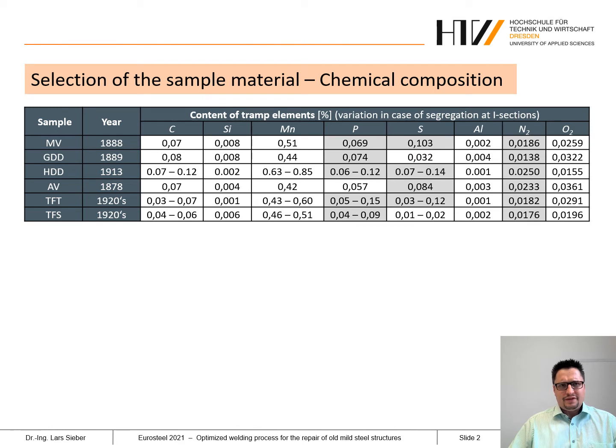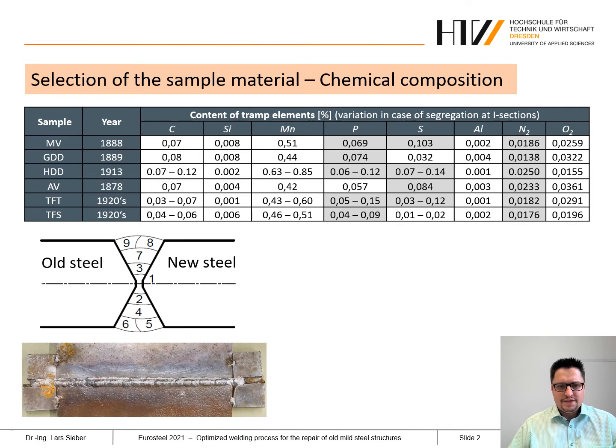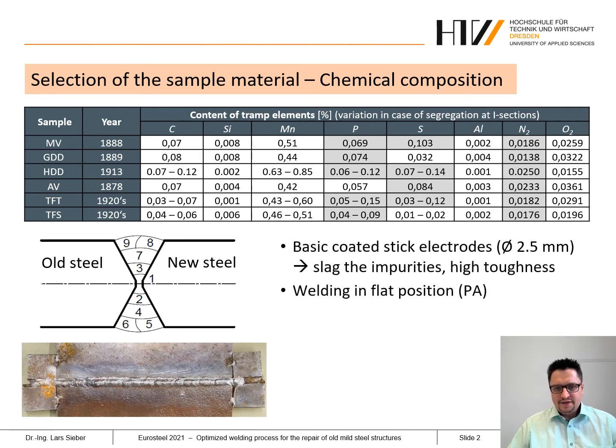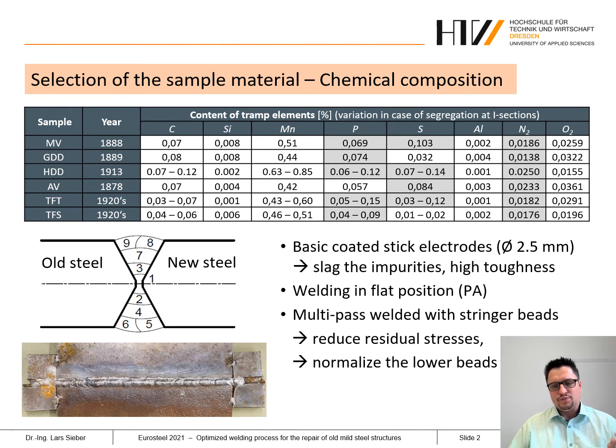At the beginning, we started with very favorable welding conditions for the butt welding. That means we used only basic coated stick electrodes with a small diameter, 2.5 millimeters, because these basic electrodes slag out the impurities in the segregation zone and give the weld metal proven high toughness. We only welded the butt welds, as you can see here on the left, in flat position, and we performed only multipass welding with stringer beads to reduce the residual stresses in the welding and also to normalize the lower beads.